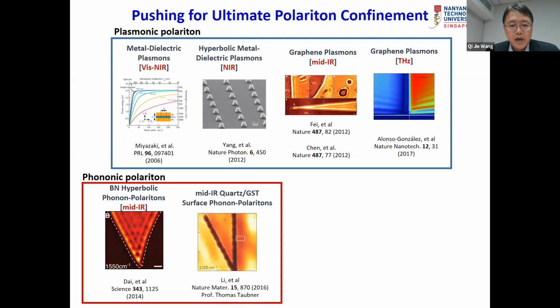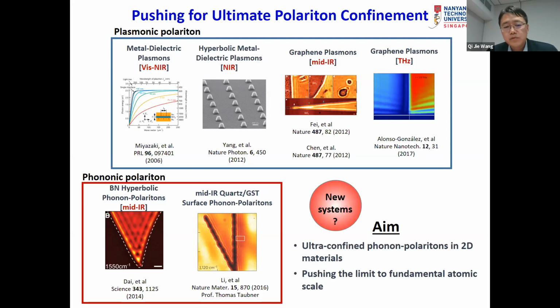And very recently, a very interesting and promising platform was demonstrated by Professor Thomas Taubner's group by using high refractive index GST, which is a phase change material, on a quartz substrate to achieve highly confined phonon-polaritons. And because GST is a phase change material, they also showed the tunability of such a device. So I would say this is really excellent work that motivated us to do the phonon-polariton research that I'm going to present later. However, at that time, our question was that in such a system, the eventual device performance is limited by the material quality at the nanoscale. So our question is whether we can find a new system to achieve ultra-confined phonon-polaritons